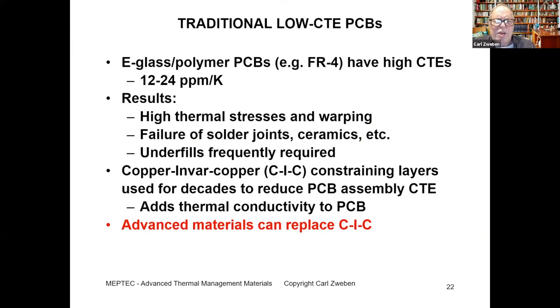If we look at printed circuit boards, e-glass polymer printed circuit boards, very widely used in the industry, of course, they all have high CTEs, again, in the range of 12 to 24 parts per million per degree Kelvin. As a result, we get high thermal stresses and warping, failures of solder joints, and actual failures of ceramics. And to get around this, we typically require underfills.